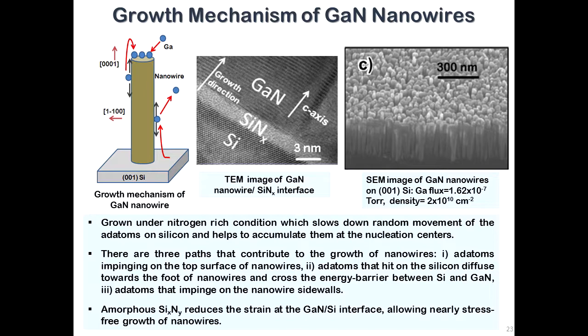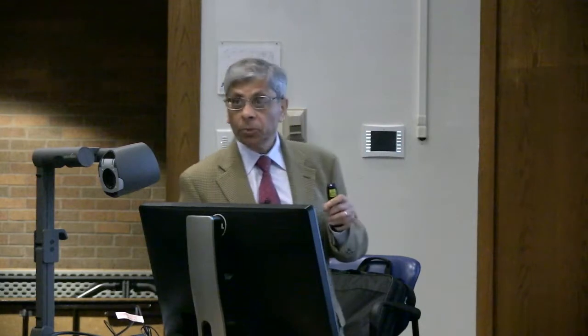When you start the growth, there is first a competition between the silicon-nitrogen bond and the gallium-nitrogen bond, and the silicon-nitrogen bond actually wins. And you form this very thin silicon nitride layer. And this does a lot of things. This silicon nitride layer kind of isolates the subsequent growth from the substrate, and the epitaxial requirements are removed.